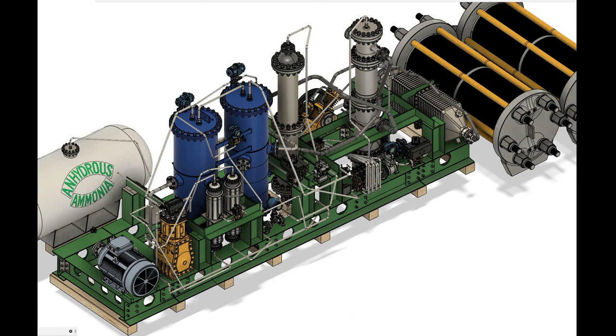The hydraulic section consists of a cylinder and piston assembly, which pressurizes hydraulic fluid to drive the metal diaphragm, which compresses the gas on the other end. The standard lifespan for diaphragm compressor diaphragms in MTBO, mean time before overhaul, is limited to around 5,000 hours for standard metal diaphragms, which are usually constructed out of multiple layers of stainless steel sheet for maximum suppleness.